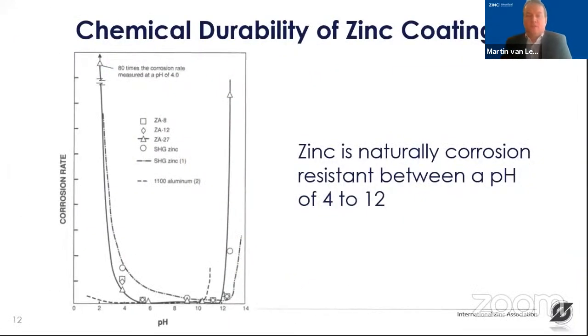Zinc is also quite durable in different chemical conditions, and zinc corrosion is very low in a pH range of 4 to 12. That means that even where the environment is a little bit acidic, like with acid rain in the past, zinc can still protect your steel against corrosion. And also in an alkaline environment, for example, concrete can be pretty alkaline. Zinc has a protective property until a pH of 12.